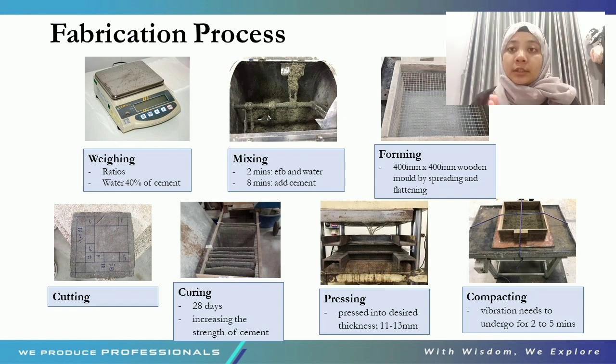After the materials undergo the weighing process, they need to go through the mixing process based on specified ratios. The mixing process will take around 10 minutes, which are 2 minutes of mixing EFB and water, and 8 minutes after adding cement.